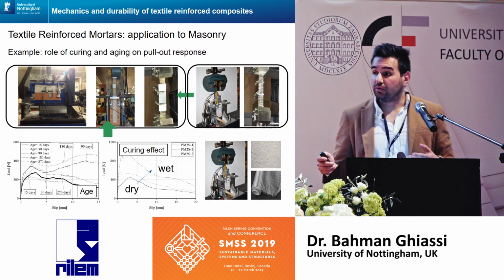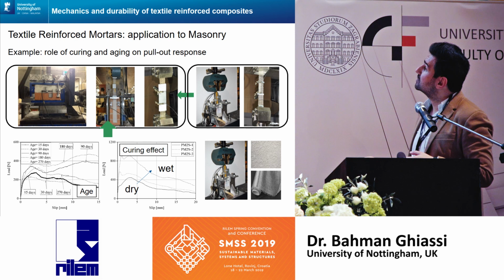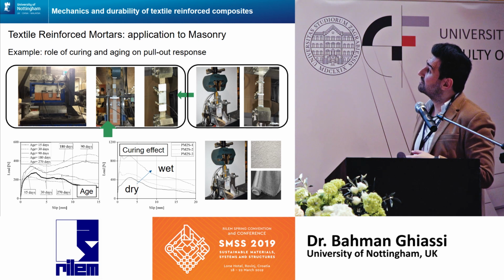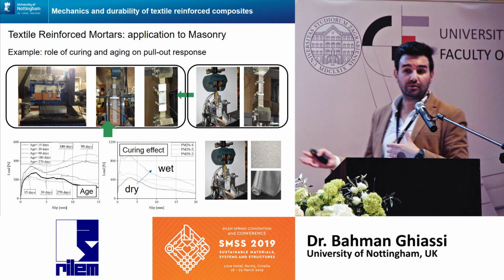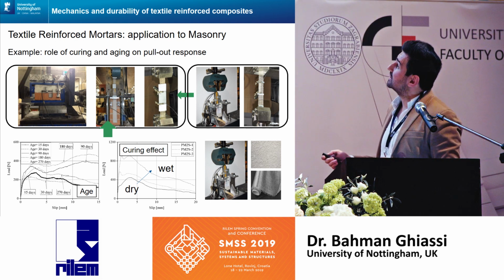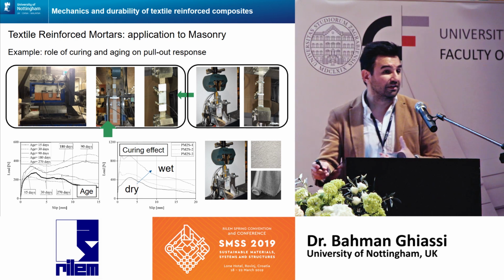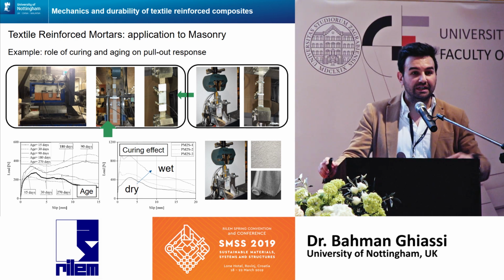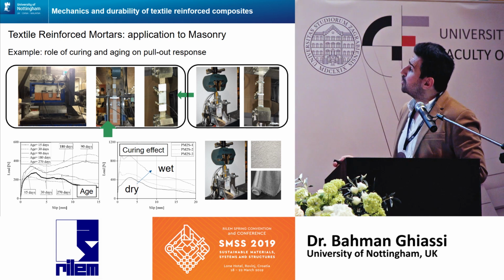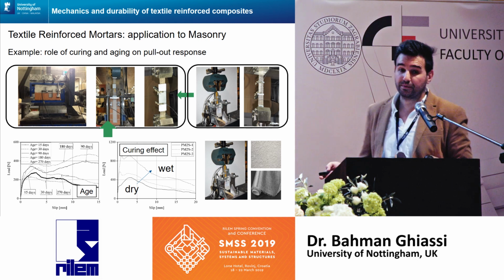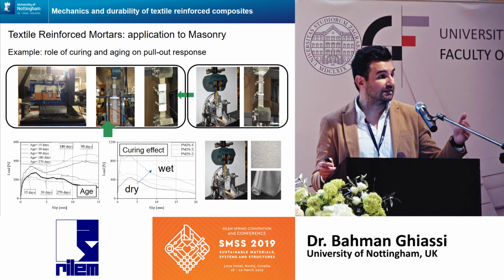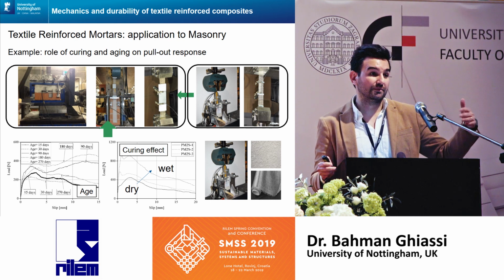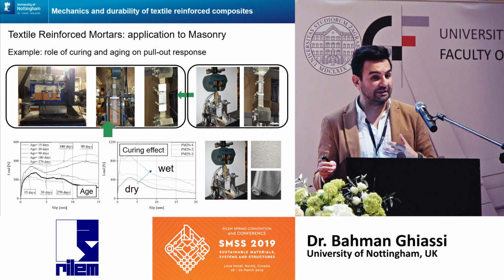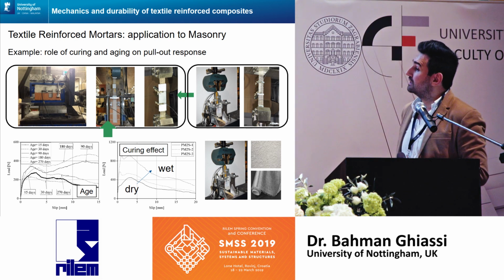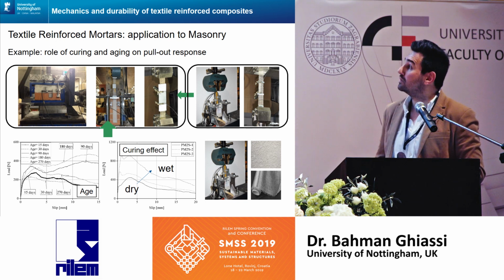So just to show you an example, I'm showing here the pull-out response of steel fibers embedded in mortar, and it shows that the curing condition can significantly affect the pull-out response of the fiber, and that consequently affects the bond slip laws that can affect the tension stiffening of the strengthening system, and then the performance of the whole structure at service, let's say. Or the mortar age can have a significant influence on the pull-out response. And that shows that maybe the 28 days testing procedure that we have been following from cementitious studies might not be really applicable to these materials and to these pozzolanic limes. So maybe we need to find new standards and new testing methodologies for these materials.